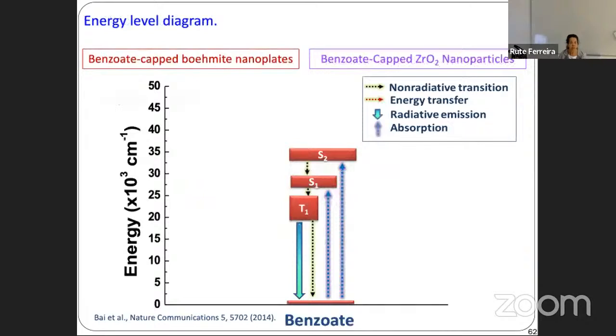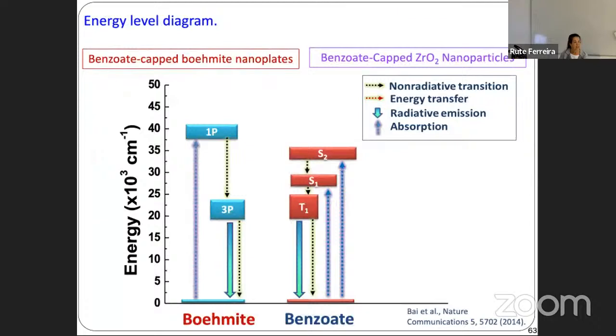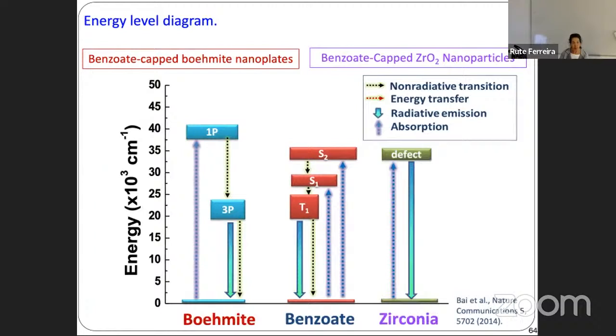In a very simplified way, we can understand the reason. I have to say that this was modeled, and you can find the calculations in the literature. And here I will explain to you the main concept from a qualitative point of view. Okay, both nanoparticles have, of course, the contribution of the triplet and singlet excited states for the absorption and emission features. And in the case of the boehmite, we must add the excited states of the F-center. And in the case of zirconia-based nanoparticles, we need only to add the singlet state related with the zirconia oxide defect.